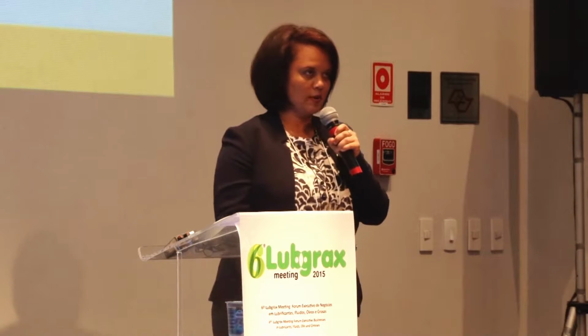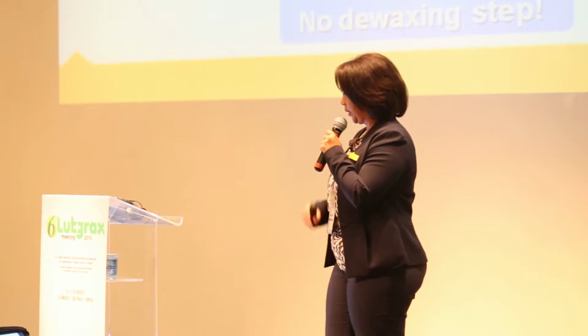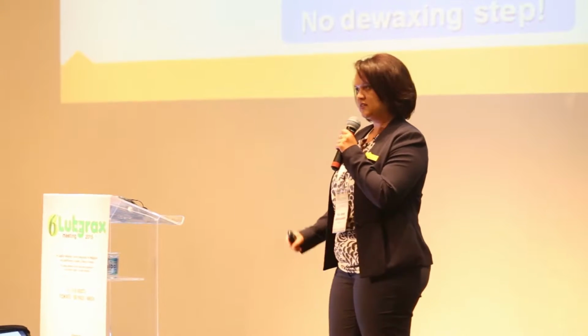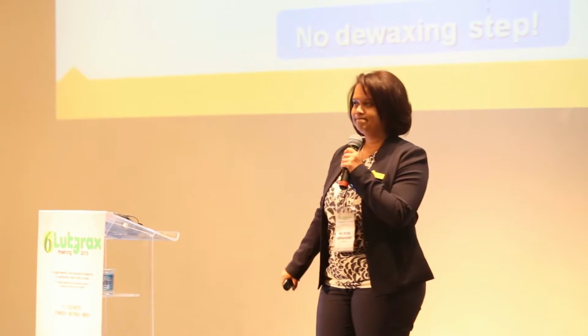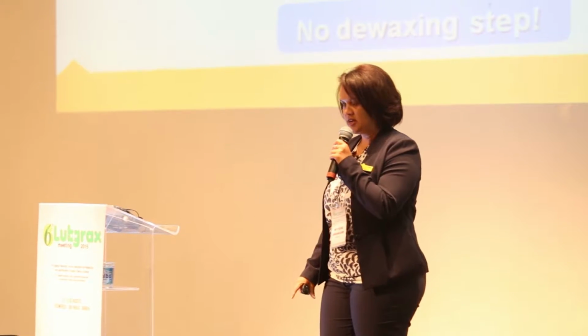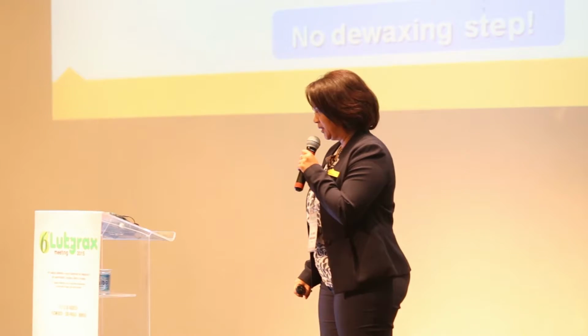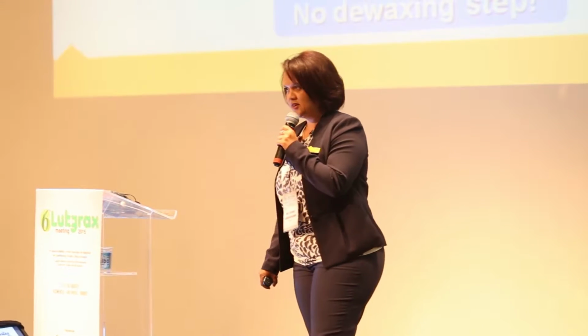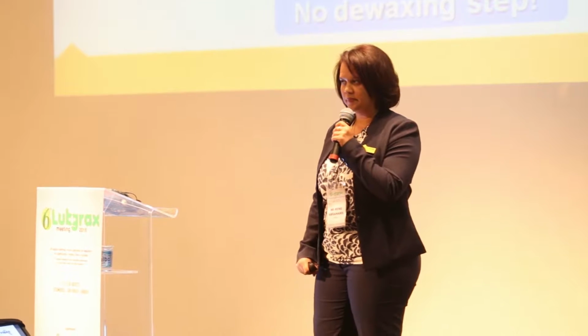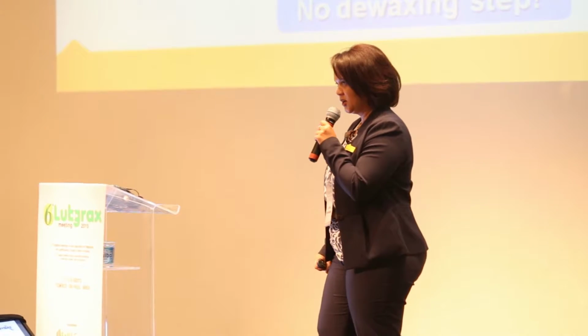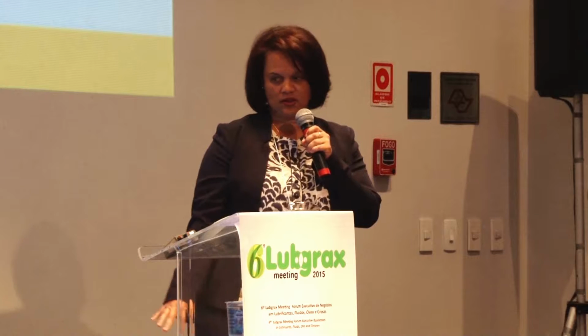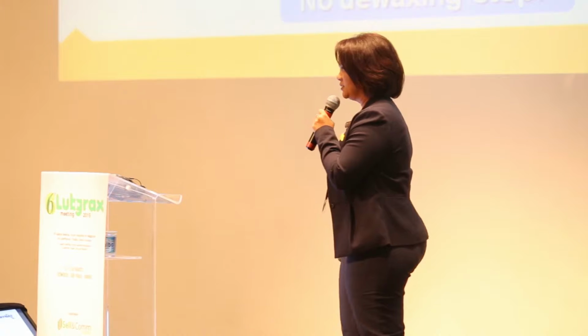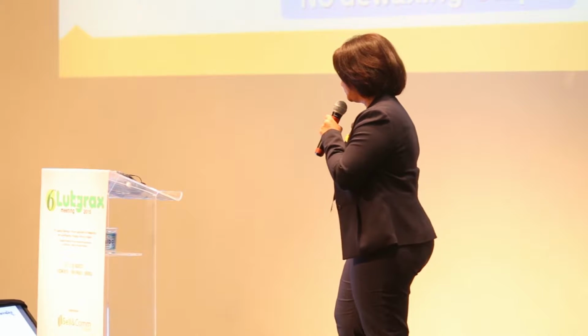If we look at naphthenic oils at Nynas, we have 2 different ways of processing the crude. Firstly, we buy a wax-free crude, which means that we do not have any dewaxing processes in our facilities. Also, we tend to buy very heavy crude, so there is no atmospheric distillation unit, but we proceed directly into a vacuum distillation. When the crude is fractionated, you can then have a solvent extraction removing aromatics, and then a hydrofinishing to remove any sulfur, nitrogen, and other impurities.